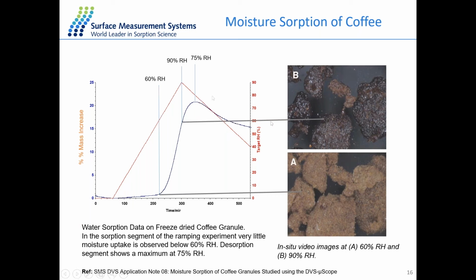And during the desorption, we can also see the increase of the mass, and the mass reached equilibrium or the maximum at 75% RH. So the deliquescence point is somewhere between 90% RH and 75% RH here. And this is a very useful plot to study the stability of this coffee granule at a certain temperature.